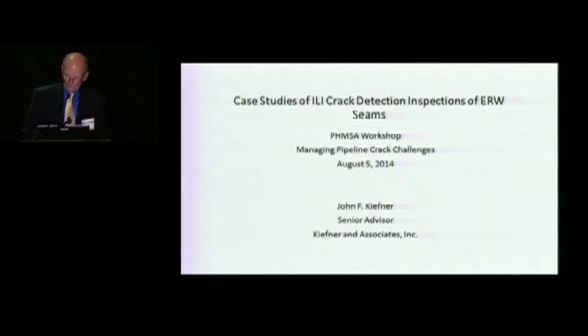And I think what we're showing here is it's not quite there, at least at the time we did this study, for ERW pipe. You can go to a paper from the 2012 IPC conference, Richard Kanye and others. I think it was basically a Trans-Canada study where they make a convincing case that they're able to handle stress corrosion cracking without a hydrostatic test. In the same paper, however, they did not make that case for ERW pipe, and that's what this presentation is about. We're not saying that it isn't the right tool for ERW, but there are some things that have to be overcome.